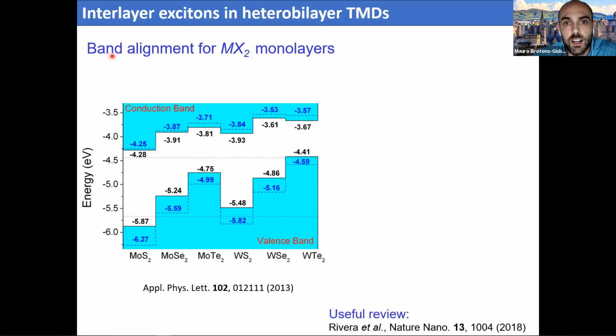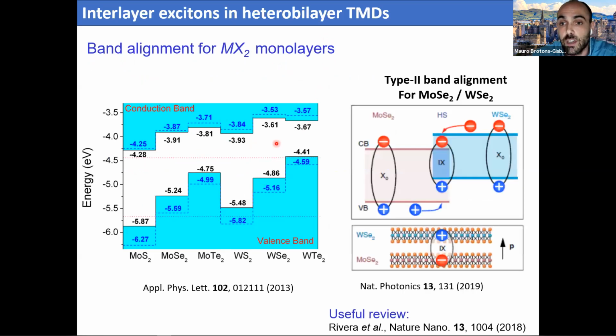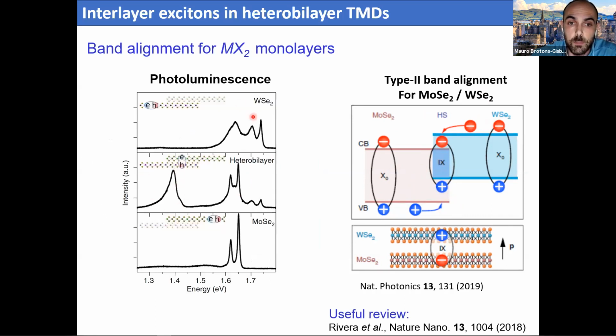What happens with transition metal dichalcogenides is that when you combine two of them, in general, you get a type 2 band alignment. In the case of the heterostructures that I'll be using, which were formed by molybdenum selenide and tungsten selenide, we end up with a band alignment more or less like this, which means that we have a fast charge transfer of electrons and holes, and this results in the formation of interlayer excitons. In these interlayer excitons, we have the electron and the hole located in two different layers. Obviously these interlayer excitons emit at lower energies than the typical intralayer excitons, so we can resolve them quite easily.